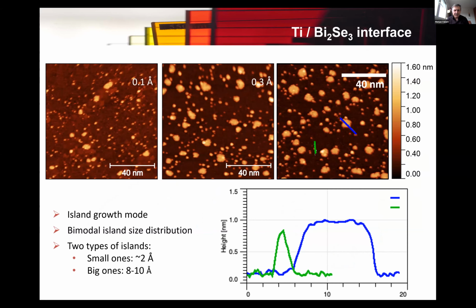Okay, now first we will stop at titanium. We analyzed titanium because it's quite often used as a first layer deposited on the surface of electronics, because it prevents further interaction with other layers that are deposited. Also in the literature, you can find a lot of cases like that, but they all report problems. So we decided to deposit titanium on the surface of bismuth selenide and analyze the interaction, if there is any.